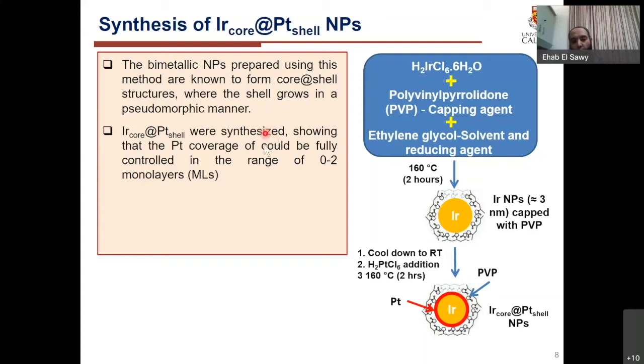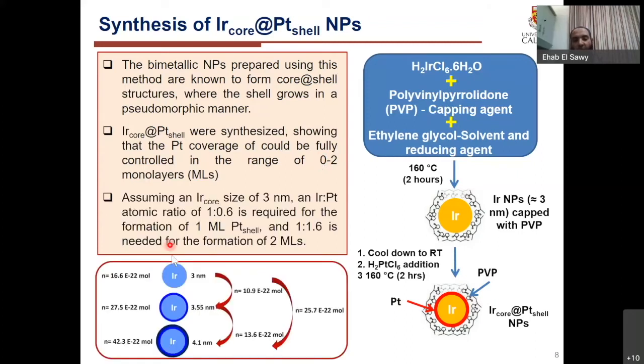So our aim was to fully control the coverage of the iridium with platinum from 0 monolayer to 2 monolayers, as I showed in the previous slide. We did that through calculations, assuming and measuring a core size of 3 nanometers. Once we know the core size of iridium is 3 nanometers, we calculated how much platinum needs to be added in this step to form a monolayer, how much to form 2 monolayers, and then we start to control the coverage.